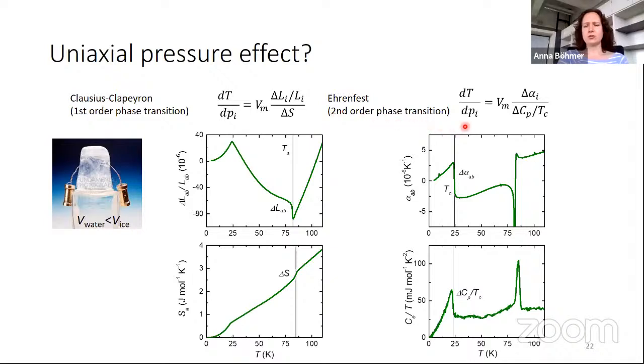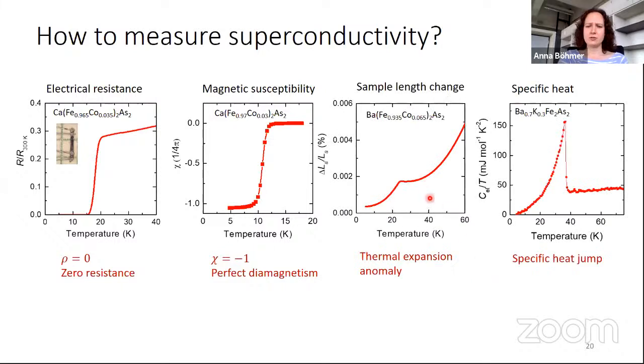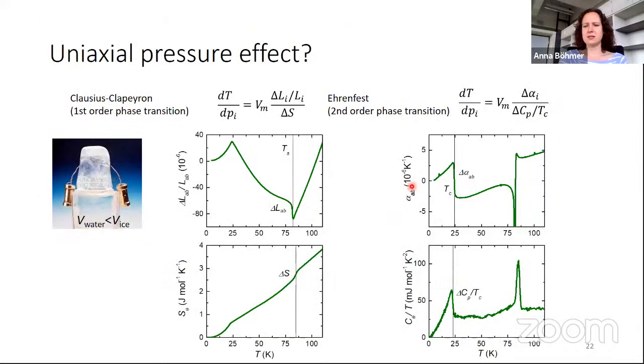You can do it too for so-called second order phase transitions, where there are rather kinks in the length or jumps in the derivative of the length, that's this alpha, and then it's called the Ehrenfest relation. Here are some examples. At this transition, the length or the volume increases suddenly, the entropy decreases suddenly. I take the ratio of the size of these anomalies and I get the pressure derivative. Here, that's a superconducting transition actually. This expansivity increases and the specific heat increases. Let me go back to show you where this comes from. This was the length at a superconducting phase transition. It doesn't jump, it has a kink. The temperature derivative of this will be a sudden change. This is very steep, this is very flat. And that's exactly what goes in here. So if we do that, what can we learn?